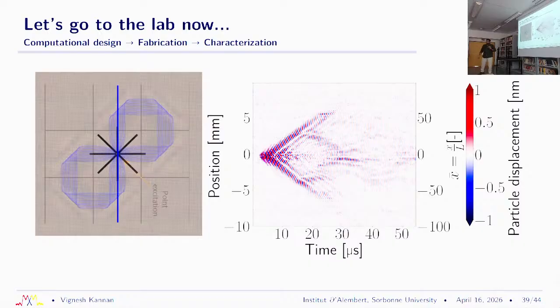The ray theory computational design said that at 750 kilohertz, I should have a figure 8. But it turns out when we did further frequency analysis, this reflection is happening significantly at about 1 megahertz, if I'm not wrong. So there is a frequency dependent response that we were discovering in the experiment that ray theory was not really looking for, and when we ran the FEM calculations for exactly those frequencies, we had perfect or nearly perfect matches.